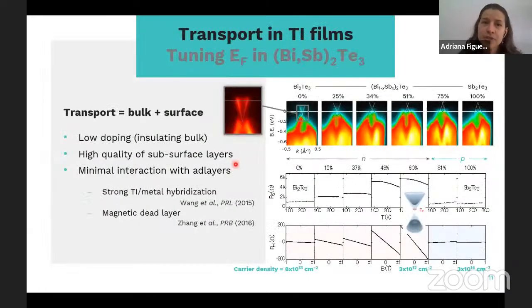Right? And in terms of transport, say magnetotransport in these thin films, this is what we are interested in. We are interested in understanding and controlling, and making sure we can exploit the transport properties of the TIs, so that we can exploit those surface states that happen at the surface of these thin films. But most of the time, in these TIs you have a combination of bulk and surface transport, because there's usually a contribution of bulk carriers in the material.